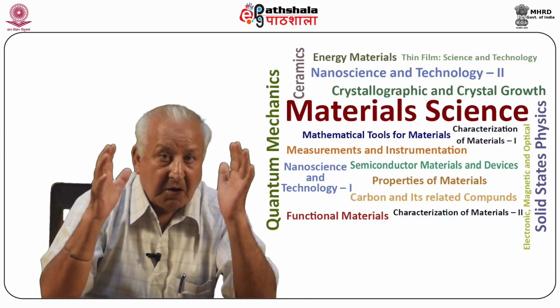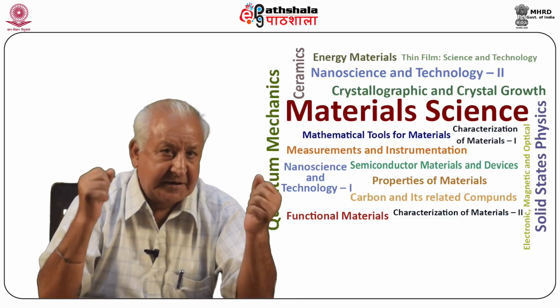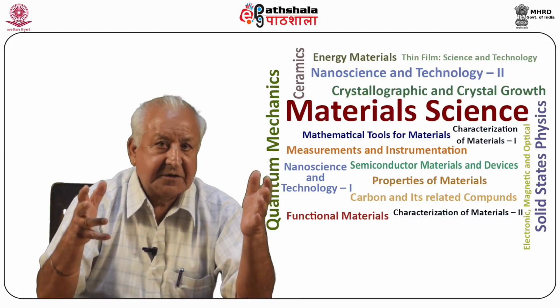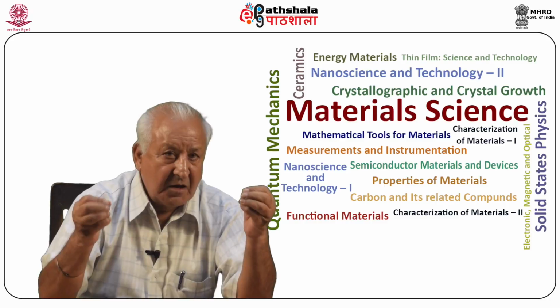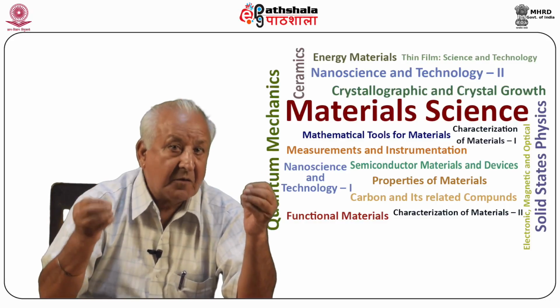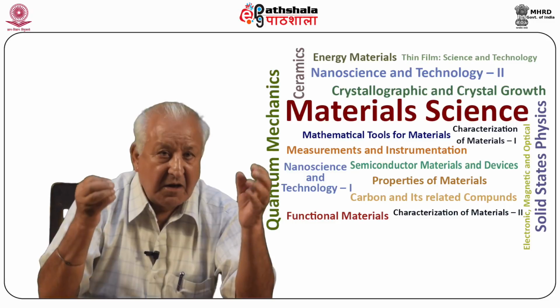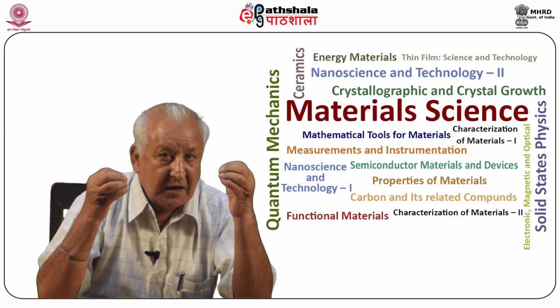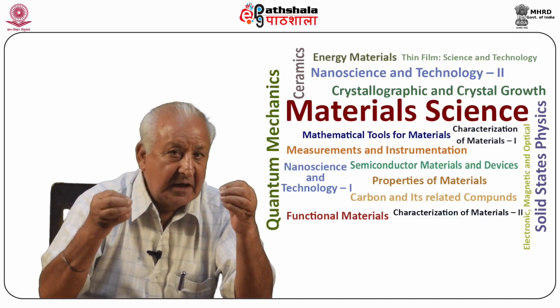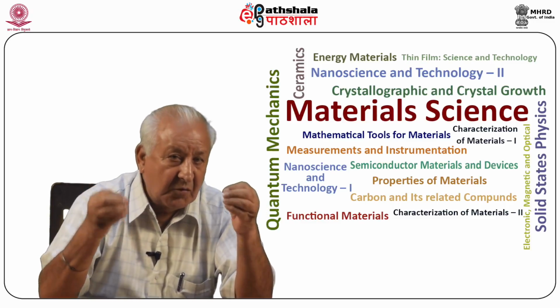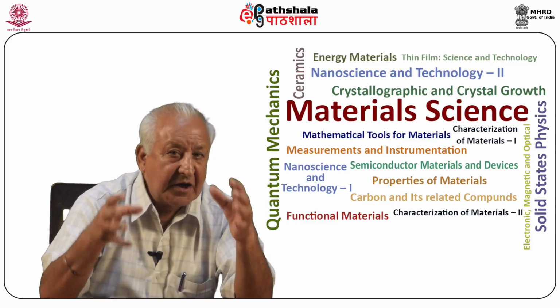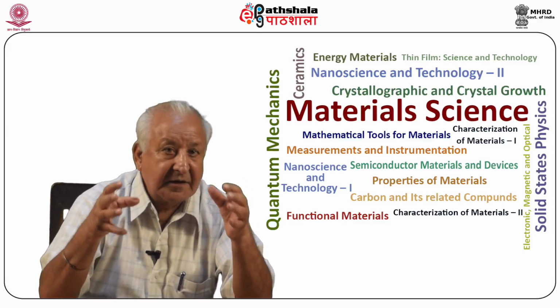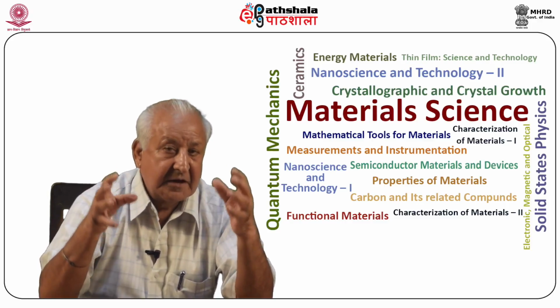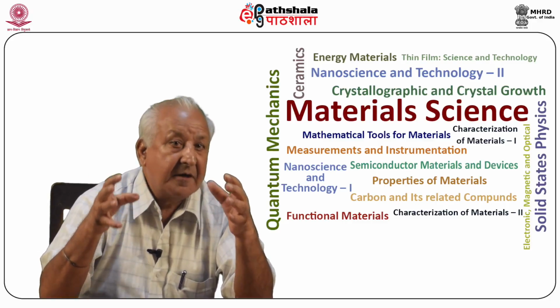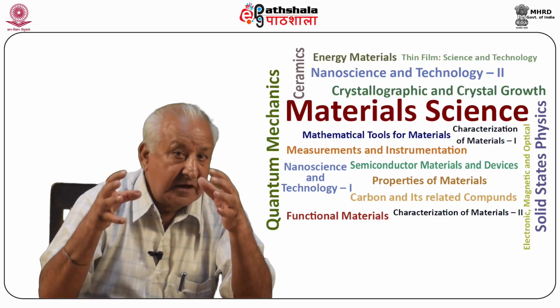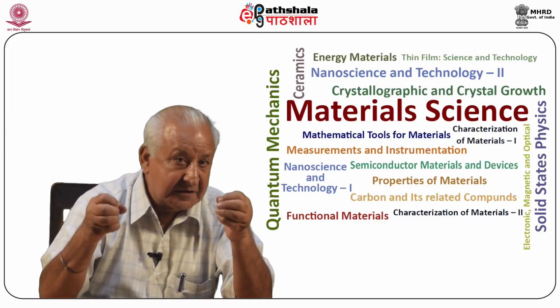Larger apertures are also used for some types of studies. Larger apertures lead to composite patterns from many crystals, which form powder rings in the case of a material that is polycrystalline with random orientation. It is known as general area diffraction, and these studies are of interest in texture and preferred orientations in materials like platy minerals such as clays.